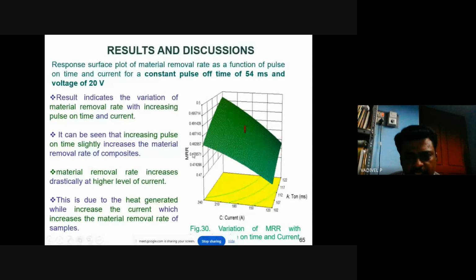Here the plot is between current, T on and MRR. Increasing the pulse on time slightly increases the metal removal rate of the composites. The metal removal rate increases drastically at the higher level of current. When the current is increased, the metal removal rate increases drastically. This is due to the heat generated when the current increases, which increases the metal removal rate of the samples. So the current has the maximum influence on the metal removal rate.